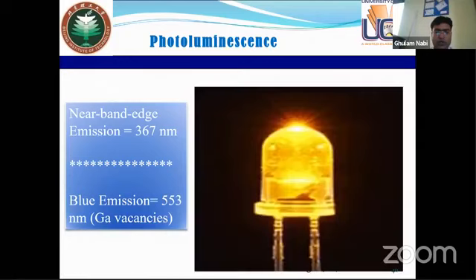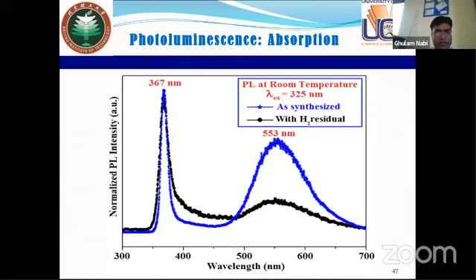So here is the last diagram, which shows that we have measured the photoluminescence before the absorption and after the absorption. The blue one is as-synthesized, and when we measure its photoluminescence after the absorption of hydrogen, you can see its peak intensity has been reduced, which is evidence that hydrogen was absorbed in the system, and the lower intensity is due to some of the residuals which have remained in the system.